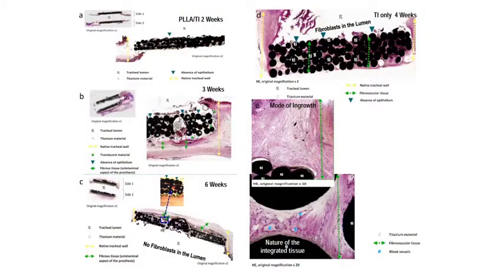Here in this figure you can see our design. As you can see, there is no clear pathway and the movement of cells and material is slow. But with the film layer and microporous structure, we are hoping to improve this. For this, the first thing we checked was histology over a course of time. What we observed is that at about 4 weeks, in the case of no polymer, cells were able to migrate into the lumen, which marked the commencement of stenosis. Whereas in the presence of the PLLA, cells were also able to move in, but they couldn't reach the lumen — it took them 6 weeks to reach half of the implant, which prevented stenosis and acted as a cushion.